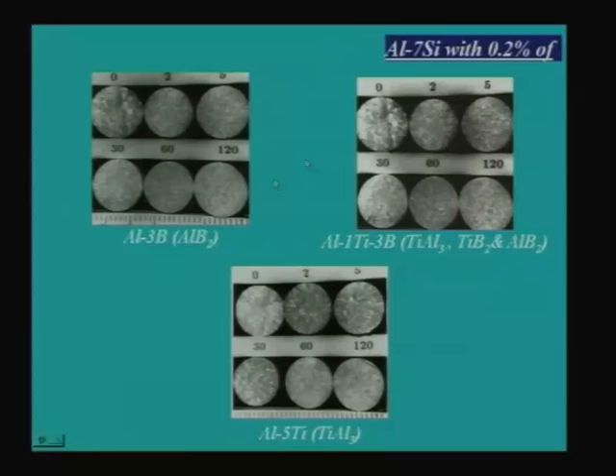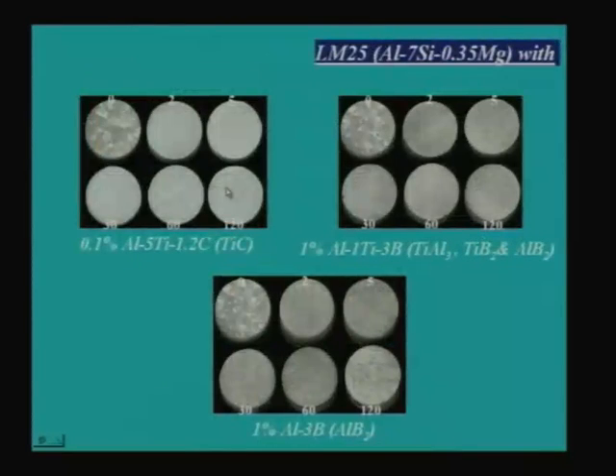And this is with aluminum boron, and this is with aluminum 1 titanium 3 boron containing different particles. This is with aluminum titanium alone containing TiAl3 particles, all with aluminum 7 silicon, to show that these are all not as good as what you get with TiC. Okay. And this is with a commercial aluminum alloy called LM25 containing a small amount of magnesium in it. Again here also you can see TiC gives you the best grain refinement when compared to all other things.